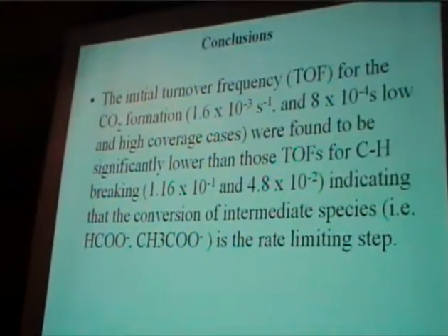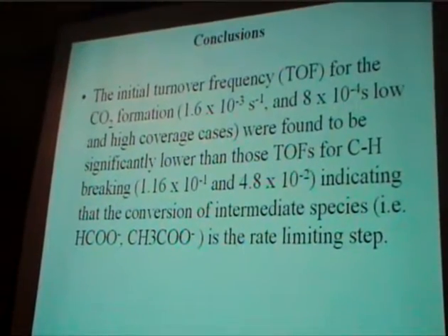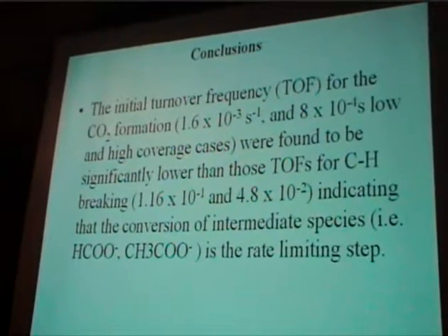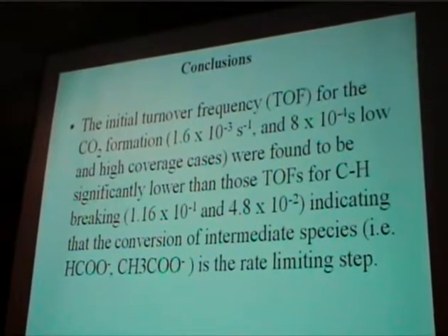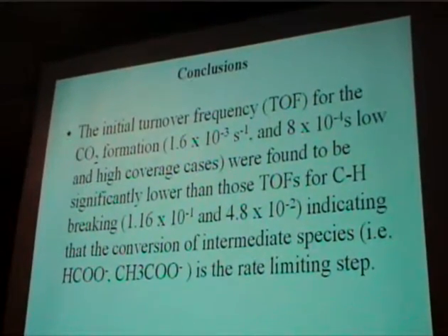And we also conclude that the turnover frequency of the CO2 formation was found to be significantly lower than that for the CH breaking, indicating that the conversion of intermediate species is a rate limiting step in this oxidation process. Thank you.